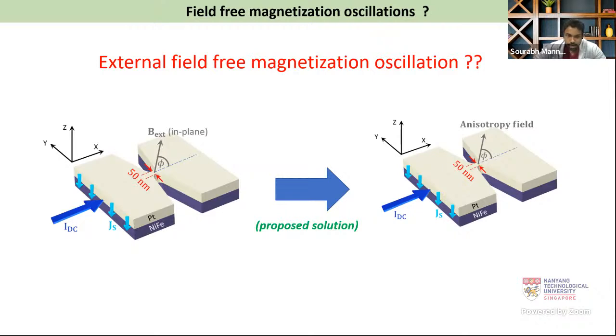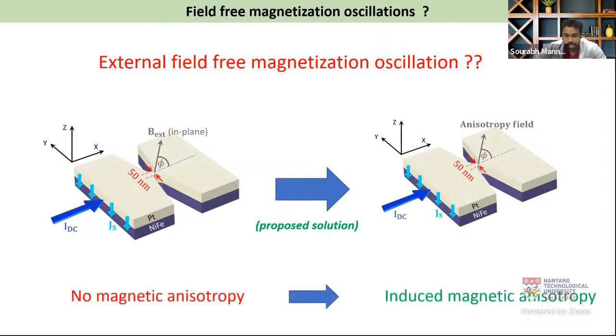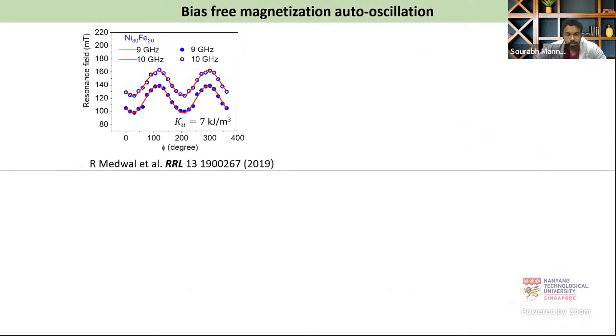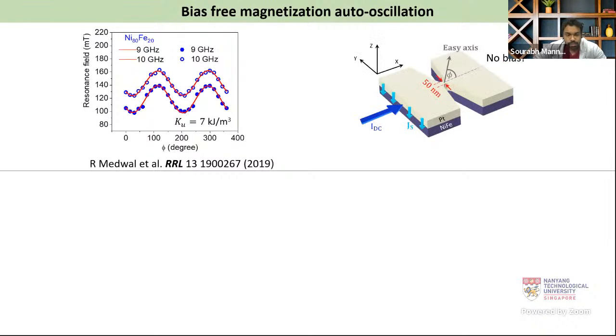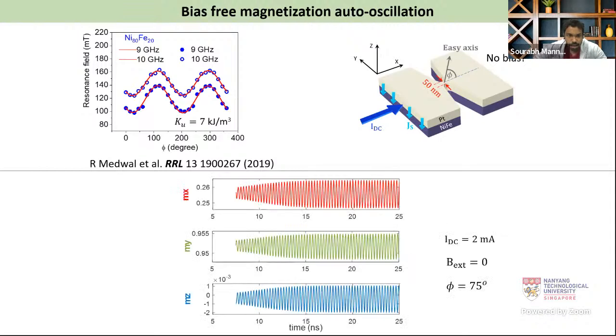Now in the permalloy layer, there is no anisotropy in general, but we can actually induce some magnetic anisotropy, as is demonstrated by my colleague Dr. Rohit Medwal in this RRL paper. And he has shown there that a uniaxial anisotropy is induced in the permalloy by modifying the deposition scheme. So we have used this anisotropy in our simulation, and we defined an easy axis, and with this we achieved the auto oscillation in a bias free condition where the external field is 0, as you can see.